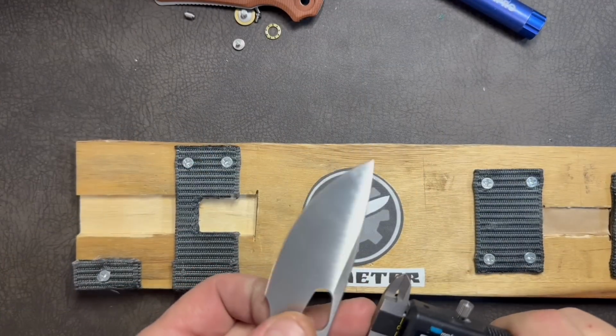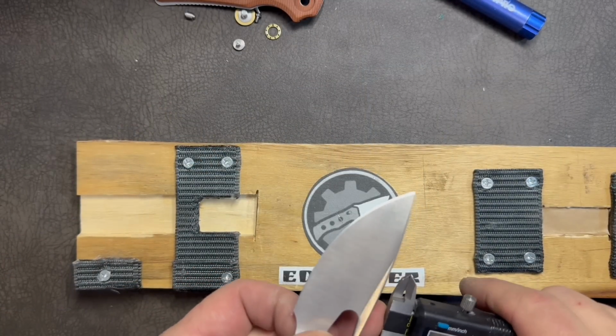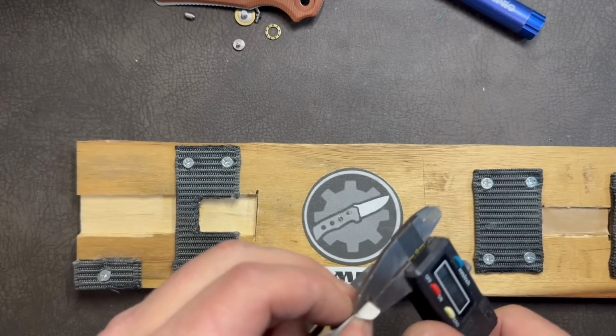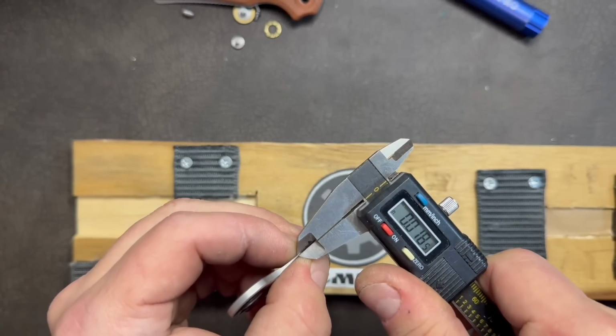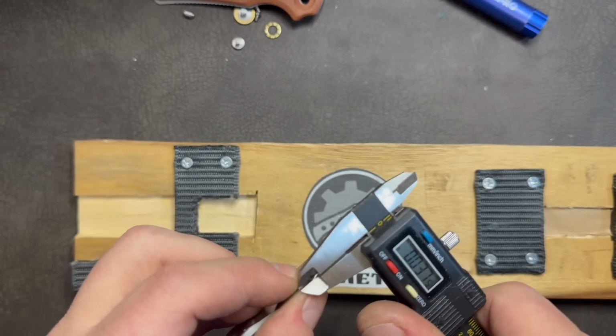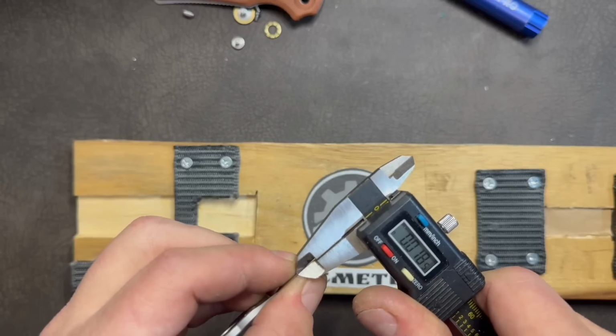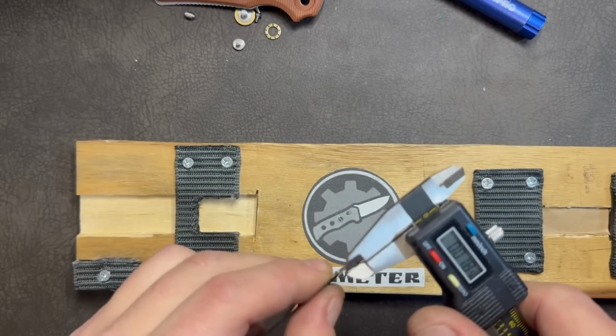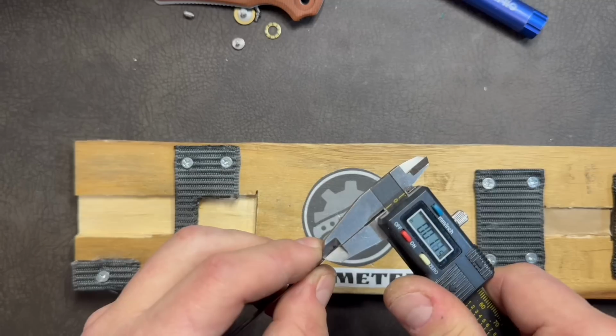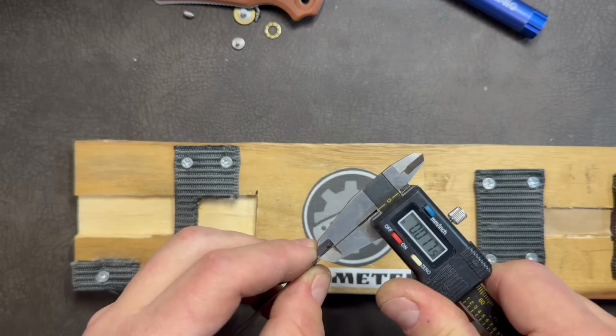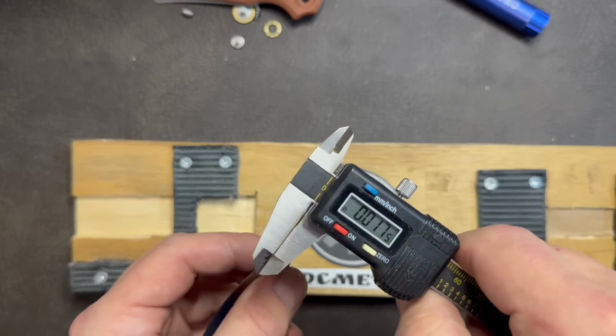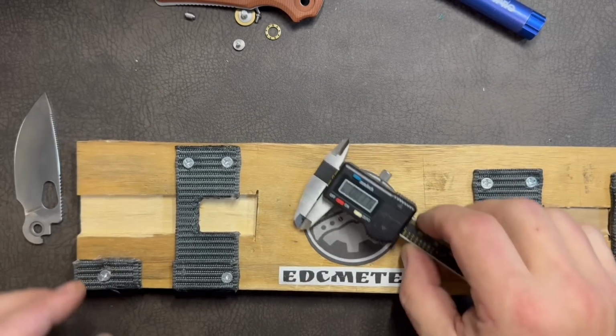This knife has an 85% flat grind primary bevel. Behind the edge thickness is 18 thousandths of an inch, and it's consistent along the entire length of the edge. Translation: the primary grind is almost to the top of the blade. It is thin behind the apex. Altogether translates into good slicing performance.